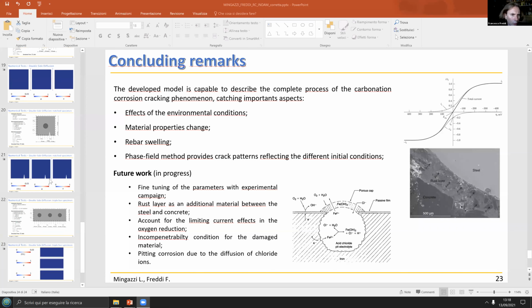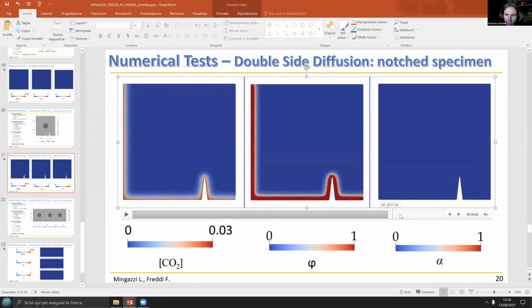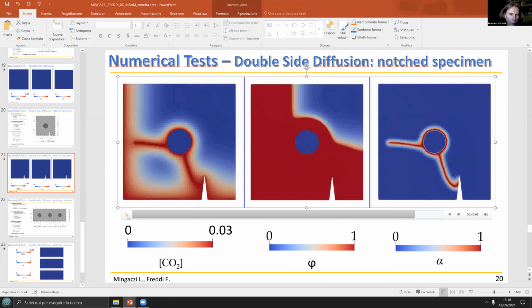I think I said it in the conclusion. I think there are some unilateral conditions that I should introduce, because there are some crack patterns that for me are not physical. Perhaps I've stopped sharing the screen, but at the end you can see the rupture around the bar. I think it's not physical, because the unilateral condition is not correctly fulfilled. For the shape of the crack, I haven't got any constraint. It just comes from the minimization of the functional, where the crack pattern is completely unknown and is given by the evolution of the damage parameter. I don't know if I answered your question. Yeah.